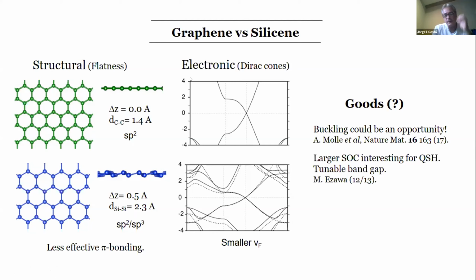bonding. Okay, if you look at the electronic structure, this is the well-known Dirac cone of graphene, and this is the band structure of freestanding silicene. The dashed lines are without corrugation, and the solid line with corrugation. You see that in both cases, freestanding silicene does show a Dirac cone, although with a much smaller Fermi velocity. So in principle, the corrugation is not really breaking the Dirac cone, the Diracness of the system. So at the very beginning, it was considered that it could actually be an advantage.